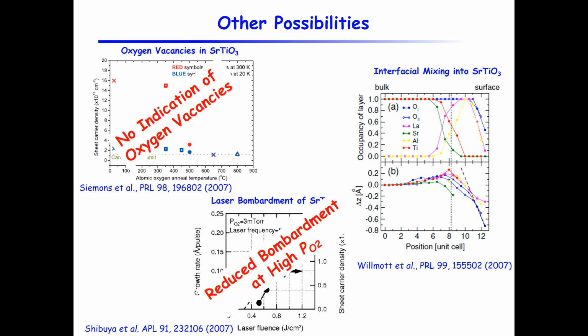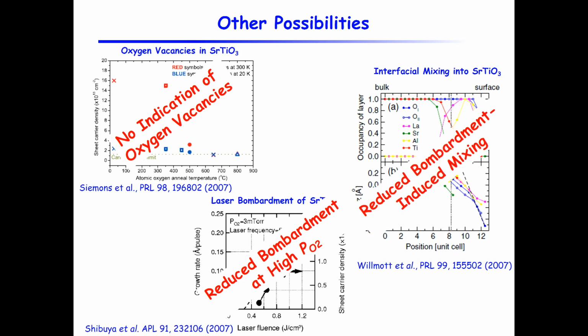Bombardment of the strontium titanate will again benefit from having higher oxygen pressure during the growth, because that thermalizes these energetic fluxes, and so this will reduce the bombardment. The interfacial mixing is something that we cannot completely exclude. We cannot rule that out completely if thermodynamics make it such that they will intermix. But on the other hand, for the intermixing caused by the bombardment, because we are using high oxygen pressure, we can reduce that induced interfacial mixing.